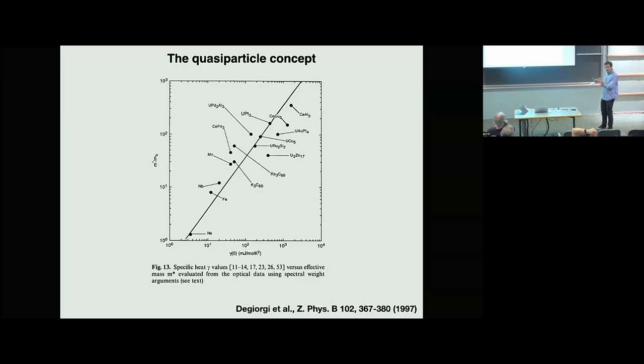It's a bad plot because it overstates the case for what we might actually believe. For one thing, it's log-log, and there's a lot of scatter, but the other aspect is that even within the level of Fermi-liquid, we don't necessarily expect that if we have an experiment that we've interpreted in the context of quasiparticles and infer a mass from that, that those masses will be the same for very different experiments, right? So quantum oscillations and heat capacity experiments might measure some kind of thermodynamic mass, which is sensitive to the density of states at the Fermi energy.